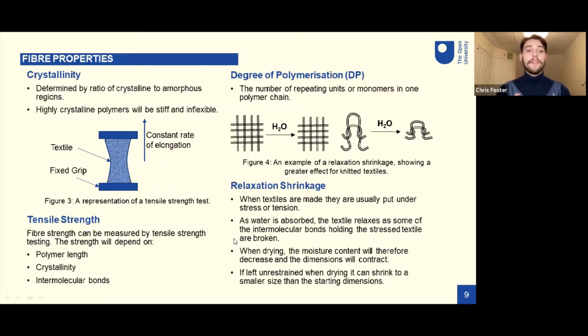So the ratio between these crystalline and amorphous regions actually determines a property called crystallinity. And usually a polymer that has a high crystallinity will be stiff and inflexible. And this is also seen with the textile as well. Crystallinity can sometimes be linked to the fibre strength, and a way to measure fibre strength is tensile strength testing. And this can be seen in figure 3.